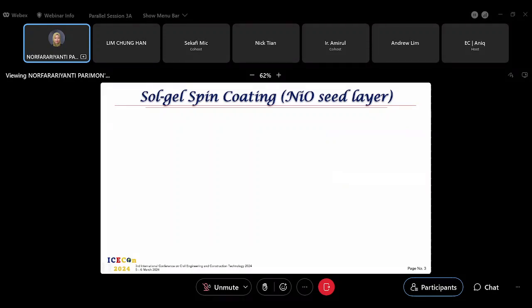This is the first step of deposition of nickel oxide nanostructures. We deposit the nickel oxide seed layer first before we grow the nickel oxide nanoflowers. We use sol-gel spin coating as the seed layer, or what we call a thin film, to improve the adhesion of the nickel oxide nanoflowers.